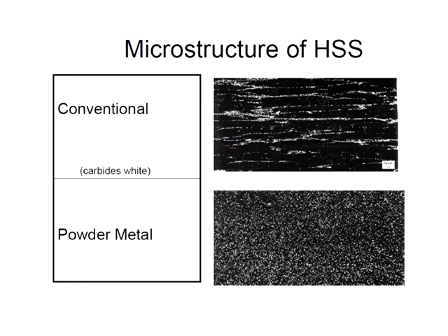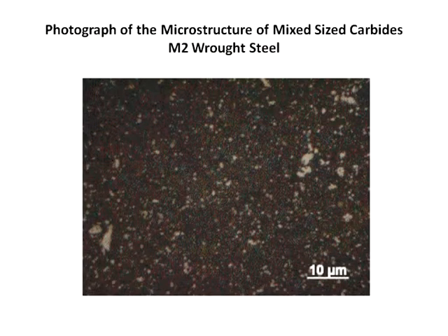Your microstructures. This is a conventional, like an M2 probably, or an M4. You can see in the wrought product on top, it's elongated. The carbides, the whites, are longitudinal. In the powdered metal, it has no directionality. It's nice and equiaxed. No matter where you cut it, you're going to get nice, fine, round, dispersed carbides, which means the properties in all directions are the same. You look at the size and uniformity of them, it's nice. Some others, there again, there's a wrought one. You see big ones. That's an end on.